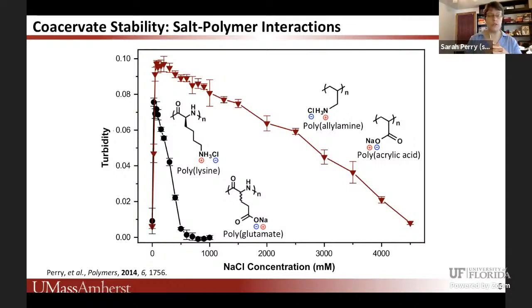You could also look at this and say, well, the charge density of these vinyl polymers is also higher, right? This is a 2-atom backbone. Peptides have a 3-atom backbone. Higher charge density, stronger electrostatics. Yeah, sure. Absolutely. And so this plot here represents an example of how it's difficult to really parse out the effects of individual chemical species when you change chemistry.